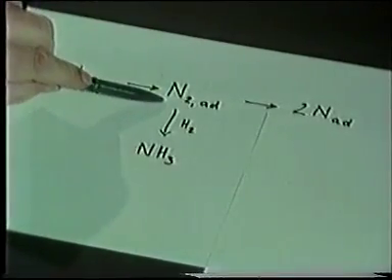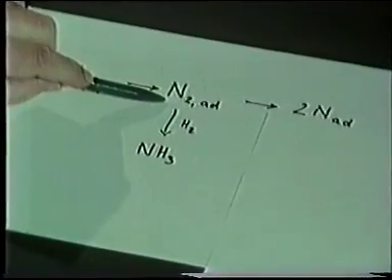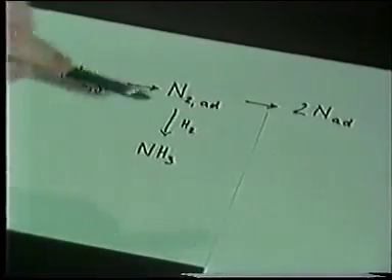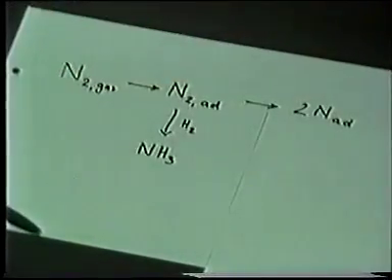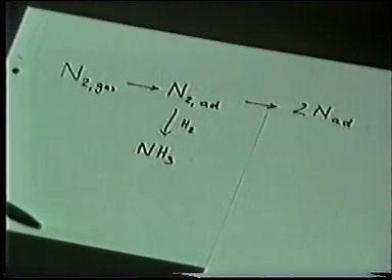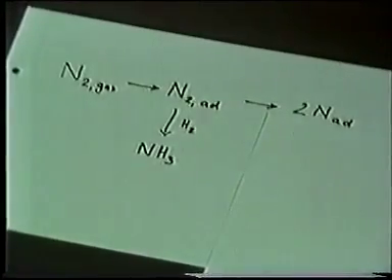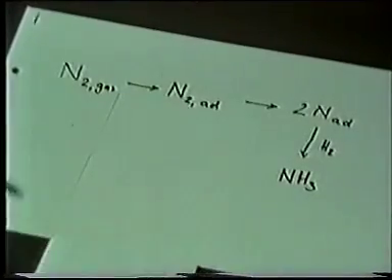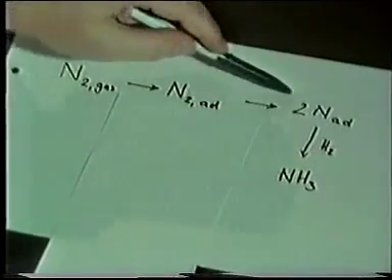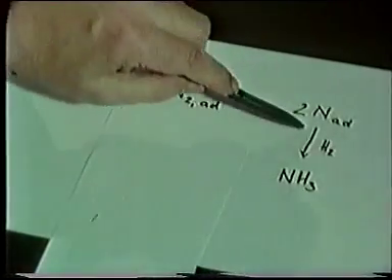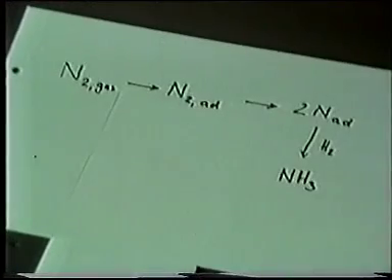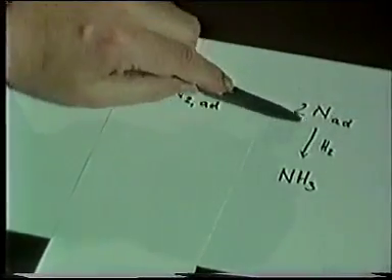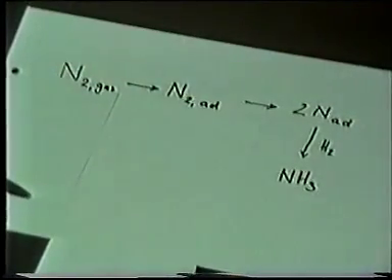Since we know that the molecularly adsorbed species also undergoes dissociation, we would also build up atomic nitrogen on the surface, and since this species is not removed in this case, it would necessarily build up to saturation on the surface. If, on the other hand, the reaction would proceed through the dissociative mechanism, the atomic species would be formed in this step, and it would be removed through the subsequent hydrogenation reaction. And as a consequence, the steady-state concentration of atomic nitrogen should always be below the saturation value.